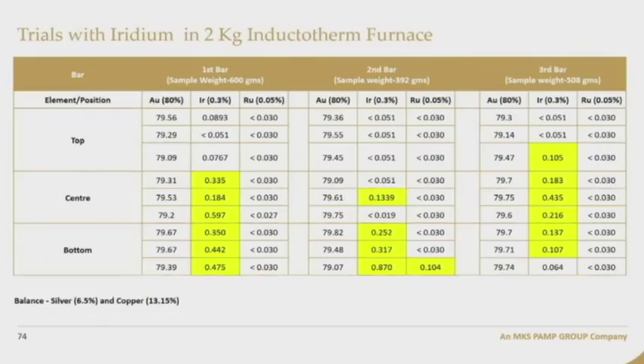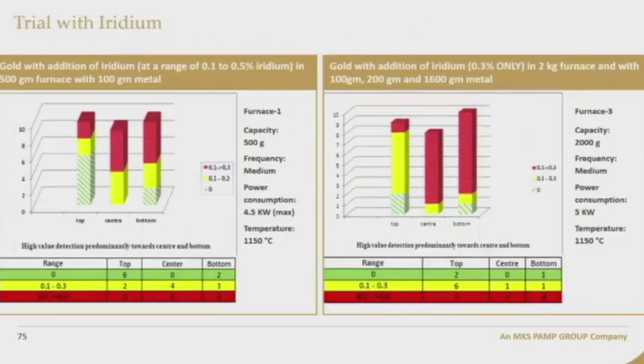We did the same thing by increasing the weight of metal. We thought whether the weight of metal would have any effect, so we used a 2 kg furnace. Again, the trend was the same: the presence of iridium was more at the bottom at the center. This is a typical bar chart when we analyze at the top, center and bottom.